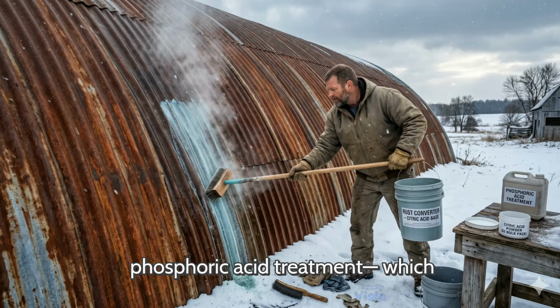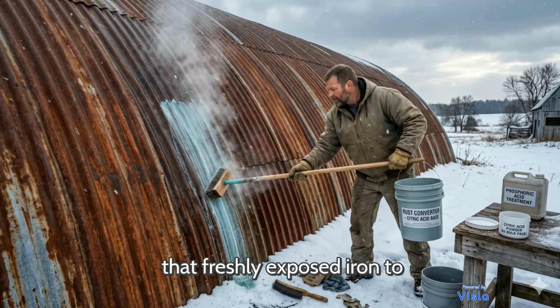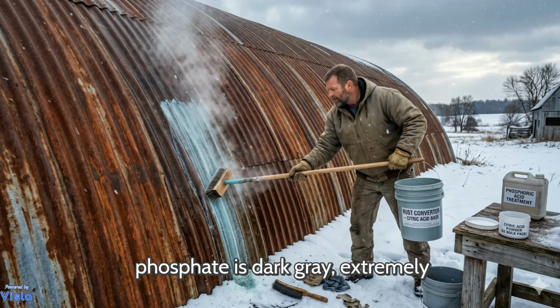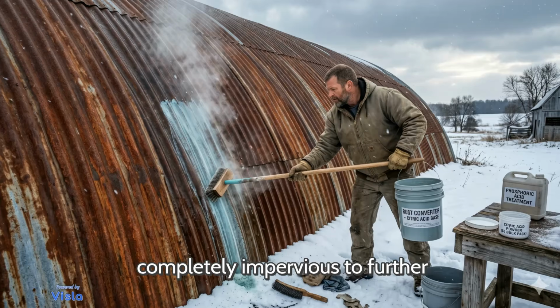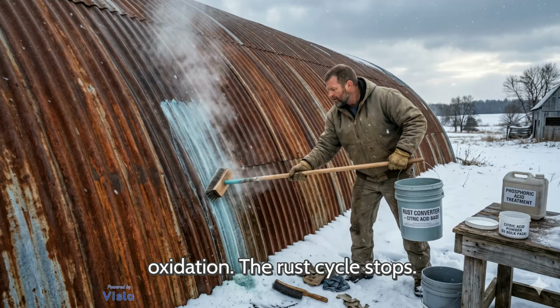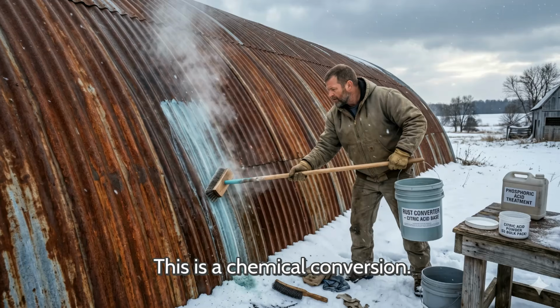You follow that with phosphoric acid treatment, which you can buy or mix yourself, and the phosphoric acid reacts with that freshly exposed iron to create iron phosphate. Iron phosphate is dark gray, extremely hard, chemically inert, and completely impervious to further oxidation. The rust cycle stops. Not because you covered it, because you ended the reaction permanently at the molecular level. This is not a coating. This is a chemical conversion. The surface doesn't just look different. It is different. That's the distinction the contractors don't want you making, because once you understand it, you realize that most of what they sell is cosmetic, surface level, temporary.